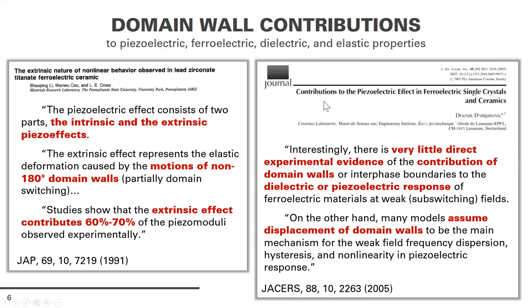And then later on during my postdoctoral days, I read this great paper from Dragan Damjanovic, a feature article in the Journal of the American Ceramic Society, which says that interestingly, there's very little direct experimental evidence of the contribution of domain walls or interphase boundaries to the dielectric or piezoelectric response. On the other hand, many models assume the displacement of domain walls to be the main mechanism for the weak field frequency dispersion, hysteresis and nonlinearity.